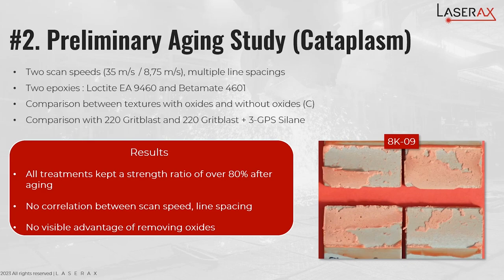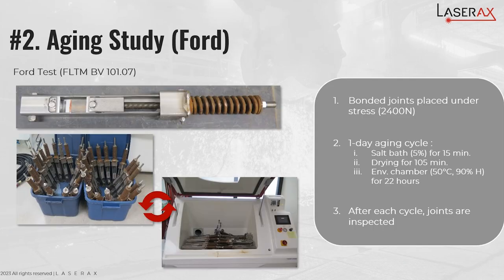The results we achieved are as follows: basically all treatments kept a strength ratio of over 80% after aging, which is really good news. However, we weren't able to see any correlation between the change of scan speed or line spacing within the laser texturing recipes. And we saw no visible advantages of removing the oxide layer. Nonetheless, this particular phase reassured us into sending some of the laser-treated samples through the second aging test — the Ford test BV101.07 — which is a much more intense aging test.